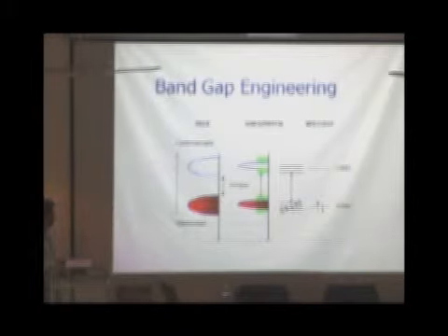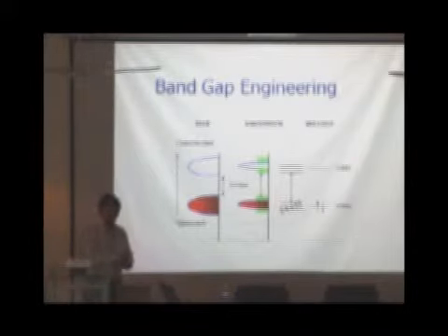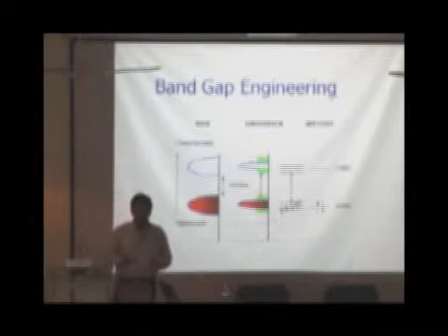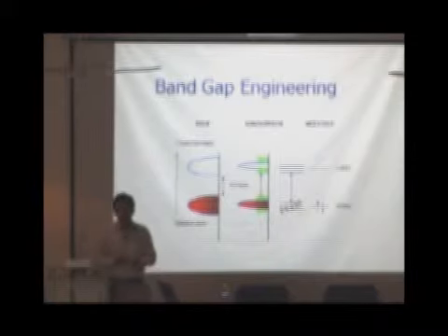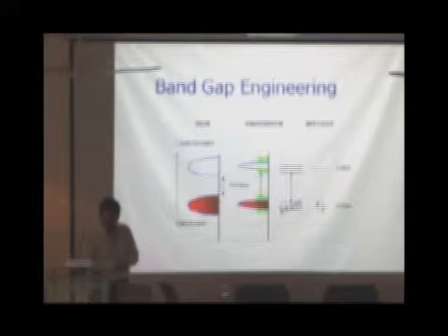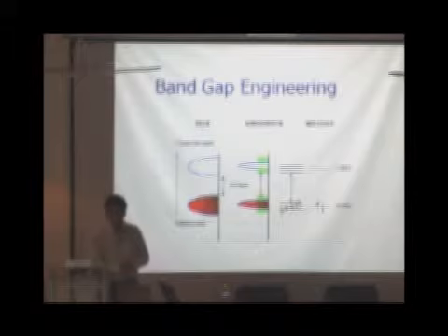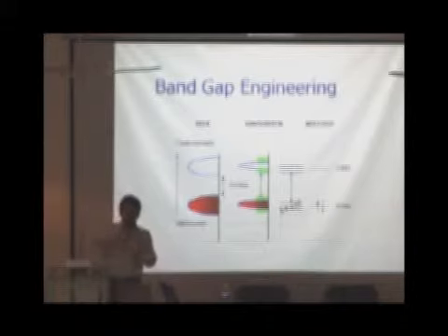But when you come to nanomaterials, when you start changing the size of these bulk materials and shrink it down, you come to a regime which is known as the quantum confined regime. In very simple words, what I can remind the students is that this is akin to a particle in a box situation, where for a one-dimensional box you have n squared h squared by 8 m L squared, and as you decrease the length of the box, you increase the energy level separation.